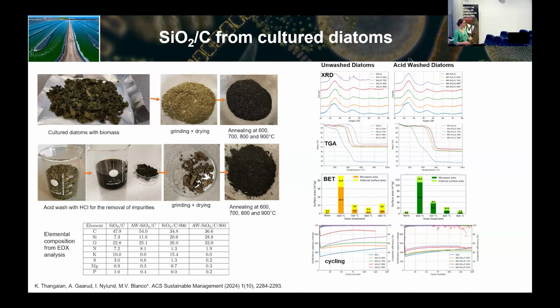So actually what now we are working on is we ask the company, when they produce the algae and they deliver to us the silica skeleton, they do two treatments. First, they get rid of most of the organic matter by some mechanical treatment, and they use some acids to burn the remaining organic matter. So now what they are doing is they prepare some samples for us without doing this second step. So maybe we can get, instead of 50% of organic matter, maybe 10%. And then maybe that will change the whole thing.